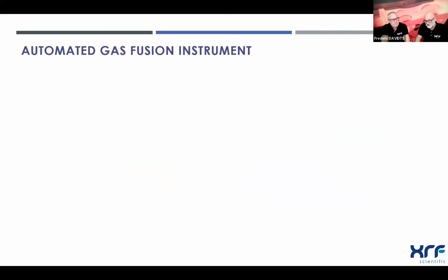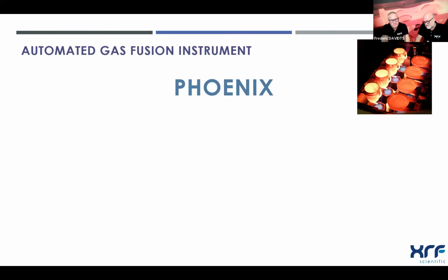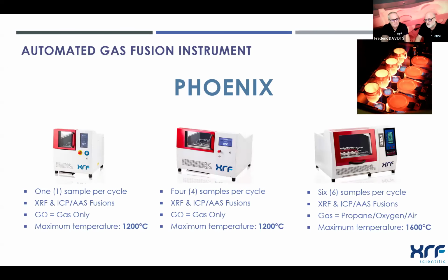And then after we have the gas fusion machine, and for that the Phoenix is our system, and we have two types of machine. First we have the Phoenix Go, available in 1 and 4 positions, and when we say Go, it means that we use gas only, so only combustible gas. So the burners are boosted with fans to push air, oxygen, into the flame, and be able to reach 1,200 degrees.